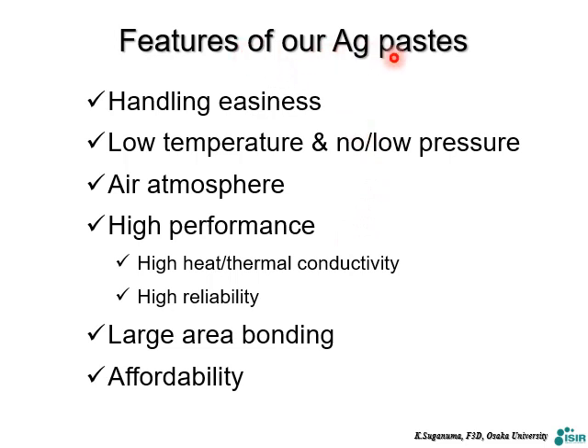The features of silver paste: handling is easy, it can be pasted easily, and the temperature is low, like 180 degrees C, with no pressure sometimes, or only very low pressure. Air atmosphere is okay, and performance is high: heat resistance and thermal conductivity are among the best, and the reliability is very good. And because of very low pressure or no pressure, large area bonding can be easily performed, and it is affordable. So many benefits from silver.